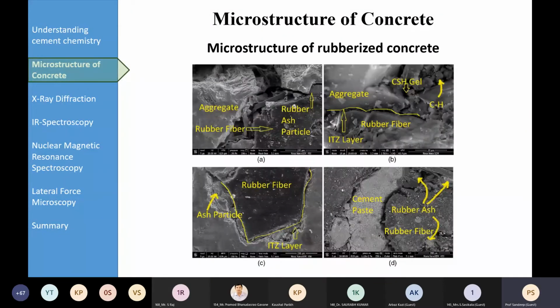Again, here this is clearly visible: this aggregate, this is the rubber ash particle, and this is the rubber fiber. And you can see this interfacial transition zone very clearly. Aggregate, this ITZ layer, very clear ITZ layer. This is a CSH gel type of structure. These platy crystals are calcium hydroxide. Here, very clearly visible rubber fiber, ash particles, ITZ layer. Here the cement paste, rubber ash here, and this rubber fiber. All these features can be observed in the scanning electron microscope.